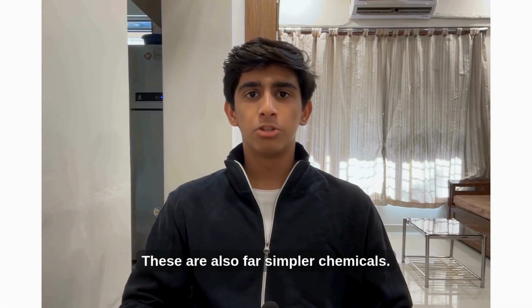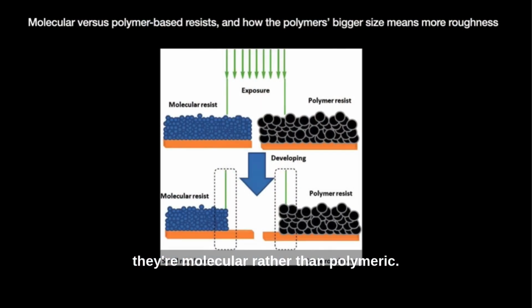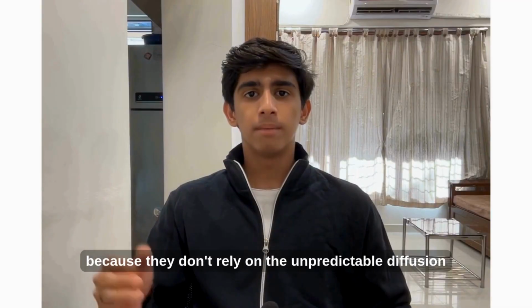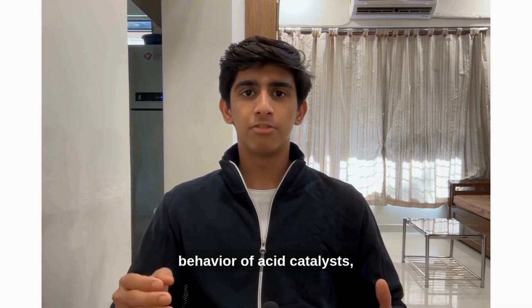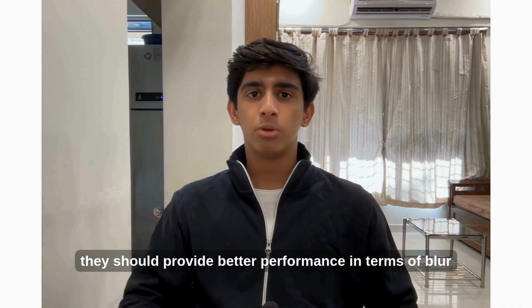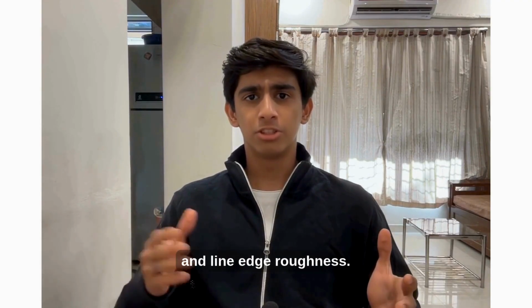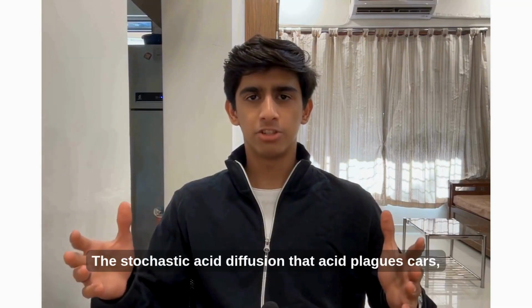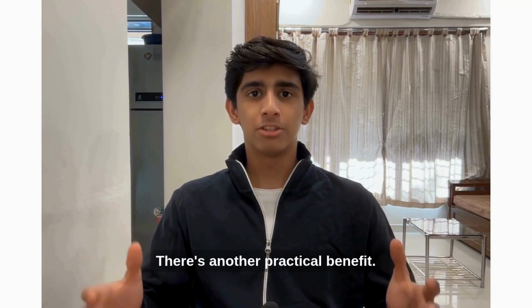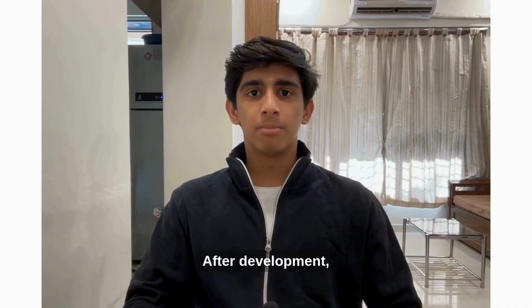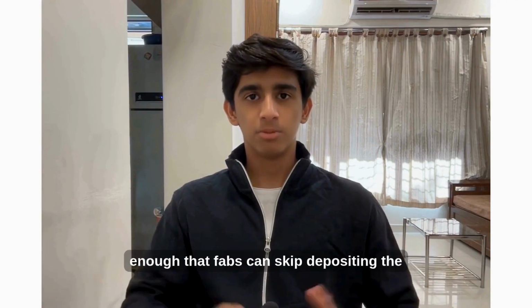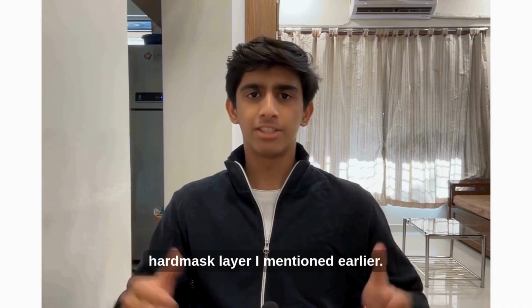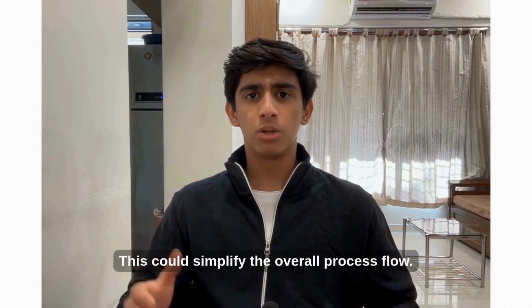But the benefits go beyond just sensitivity. These are also far simpler chemicals. Unlike CARs, they're molecular rather than polymeric. Being smaller, typically individual molecules rather than long chains, implies significant improvements in resolution and line roughness. Moreover, because they don't rely on the unpredictable diffusion behavior of acid catalysts, they should provide better performance in terms of blur and line edge roughness. The stochastic acid diffusion that plagues CARs simply isn't a factor with metal oxide resists. There's another practical benefit. After development, the metal oxide resist shell is reportedly robust enough that fabs can skip depositing the hard mask layer I mentioned earlier. This could simplify the overall process flow.